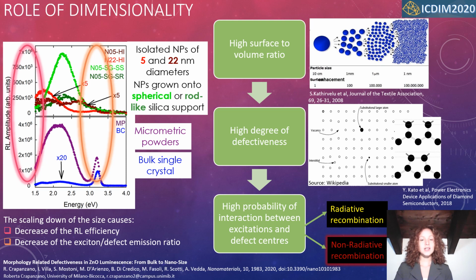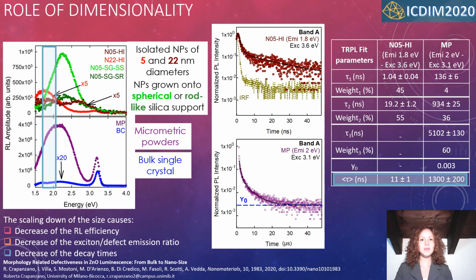Anyway, the decrease of the radioluminescence intensity observed in the nanometric systems suggests that non-radiative recombination is boosted in nano-sized materials. This result is further validated by time-resolved photoluminescence measurements. In fact, when an additional quenching channel is present, a decrease in the decay time is observed. Comparing the time decays of the same emission band of a nanometric sample and of the micrometric powders, it is possible to notice that the decay time of the nanometric sample is 2 orders of magnitude smaller than the one of the micrometric powder.